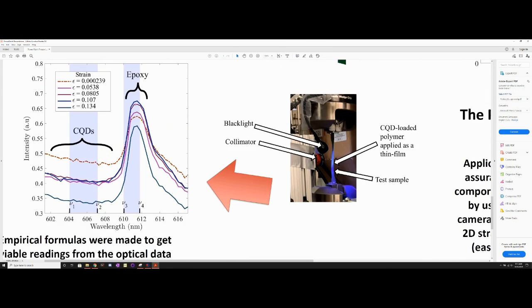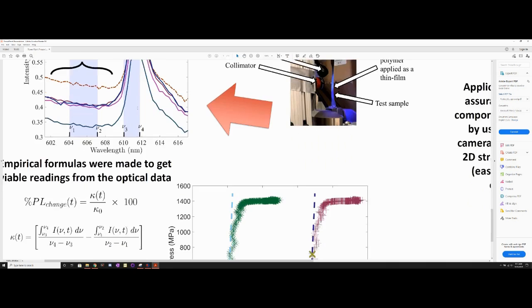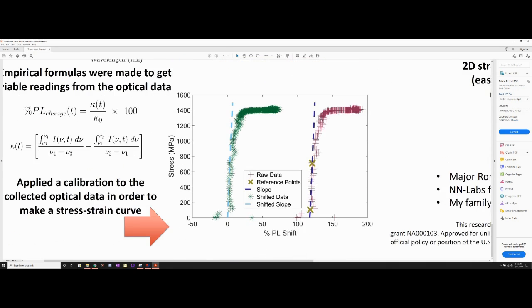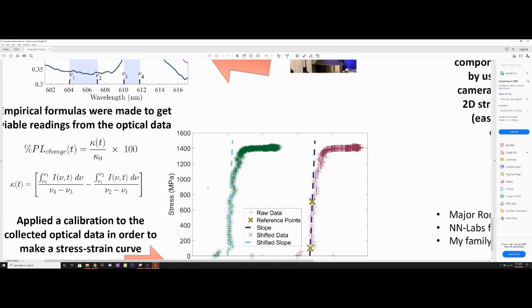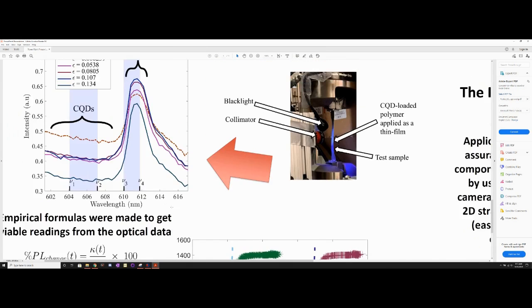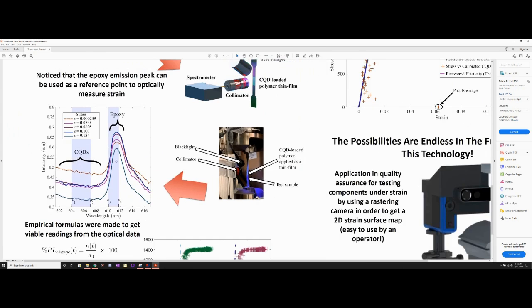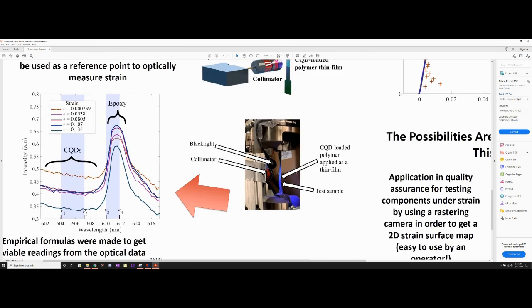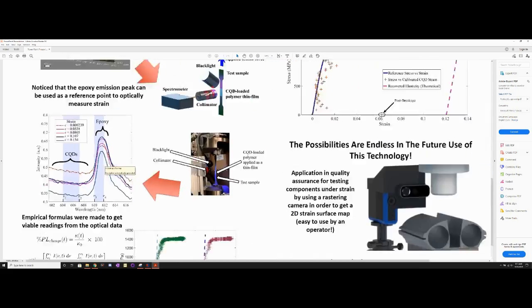And we can use some empirical formulas to go ahead and then calibrate the emission wavelengths that are here in terms of their relative photoluminescence intensities, and we can compare this to the mechanical stress strain curve and then shift it accordingly in order to get a calibration from this optical data. And what's really important is this epoxy peak, which can be used as a reference anchor point in order to help with the calibration process.